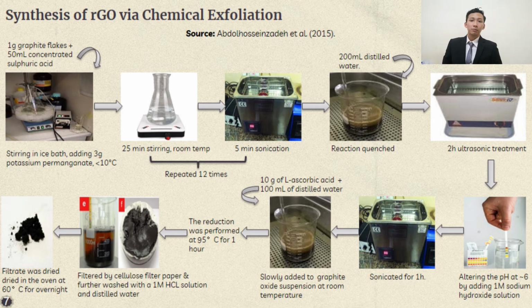The resultant black precipitates are filtered by cellulose paper and further washed with 1 mole hydrochloric acid solution and distilled water to neutralize the pH value. Finally, the filtrate is dried in an oven at 60 degrees overnight to obtain the RGO.